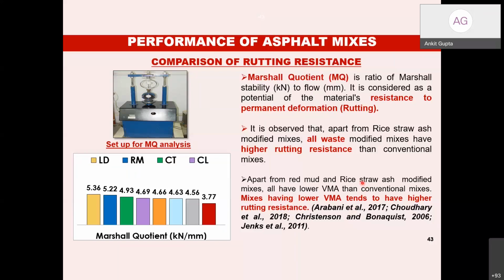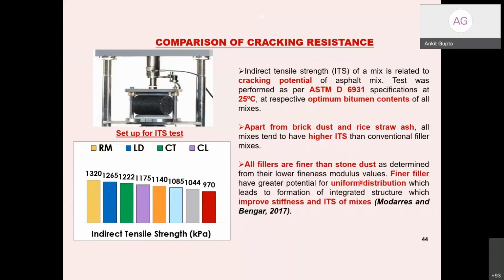Now the rice straw ash, why is it lower? Because again you'll see it is very fine. It has a lower specific gravity, and it has lower voids in the mineral aggregate. So these are the reasons that the rice straw ash had a lower value. Now coming to the cracking resistance part, again the fatigue cracking has to be checked by the UTM, the dynamic UTM. But again, we are not having that equipment.